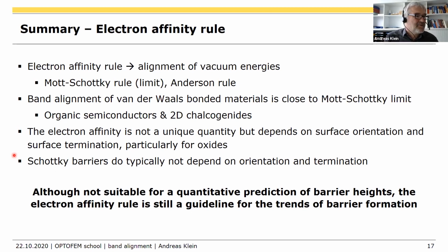Yeah, and how do I change the conduction band minimum with respect to doping? One must be careful with the term doping. In semiconductor physics, you use doping usually for dopant concentrations in the parts per million range. A 0.1% doping would be huge in semiconductors, and you can also have degenerate semiconductors with higher doping. But if you usually take a low doping concentration, this does not affect the band gap.